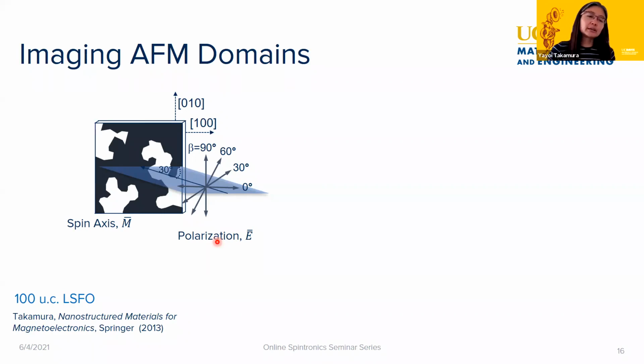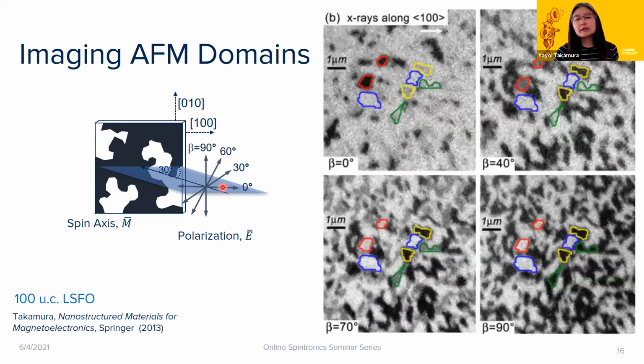And so if we're coming in with a 30-degree grazing incidence angle, right? So then vertical at 90 degrees is completely in plane. The 0-degree one is actually meaning that the E vector is canting out of plane along that 001 direction. So we can actually map in 3 dimensions where the antiferromagnetic spin axis is lying.